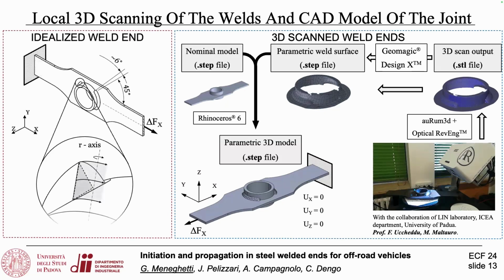But we also proceeded with the simplified option of taking an idealized joint with a weld seam with the nominal thickness and with the weld end obtained by the rotation along the weld root point of the hypotenuse of the weld seam. So we have the real scanned weld ends and the idealized weld ends.